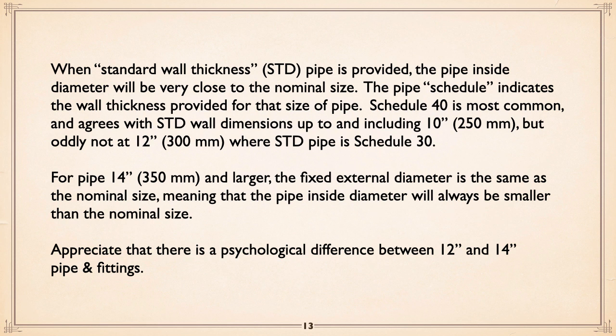Now, for pipe 14 and above, the fixed external diameter is the same as the nominal size. In other words, 14-inch pipe is 14 OD, 16 inches is 16 OD, meaning the pipe inside diameter will always be smaller than the nominal size. And I make a note here, the difference between up to and including 12-inch and 14 is a bit of a psychological barrier. A number of manufacturers change design, significantly change prices. There's a mental difference between 12 and below and 14 and above, pipe and fittings.